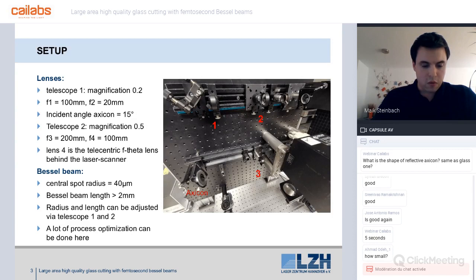This means that we adjusted the setup so that the galvo scanner with its mirrors is in between the second telescope. Lens 4 is a telecentric f-theta lens with a focal length of 100 millimeters. So the magnification of telescope 2 is 0.5. By adjusting the two telescopes, the Bessel beam can be modified, so a lot of process optimization can be done here with regard to the substrate that you want to process.